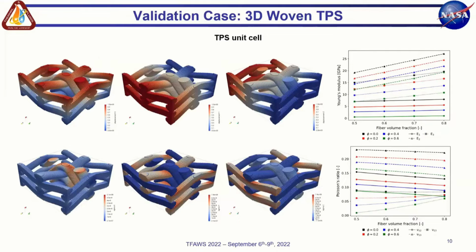The same methodology used at the microscale for the constituents was applied to obtain the effective mechanical properties of the unit cell. Again, on the top, we can observe the displacement fields, and on the bottom, the stress distribution in X, Y, and Z directions under different normal load conditions applied to obtain the mechanical properties. In these images, the matrix phase is hidden just for visualization purposes. On the right, we can observe the graphs with the Young's modulus in the 3 principal directions on the top and the Poisson ratios on the bottom, and how all these values are affected by the different matrix porosities and fiber volume fractions of the TPS. So these are some of the mechanical properties we need for full-scale modeling with PATO.